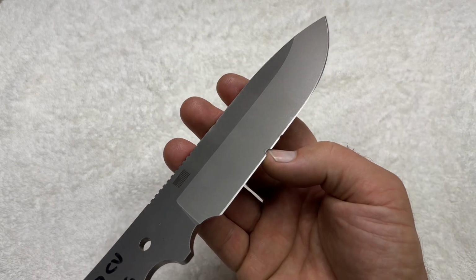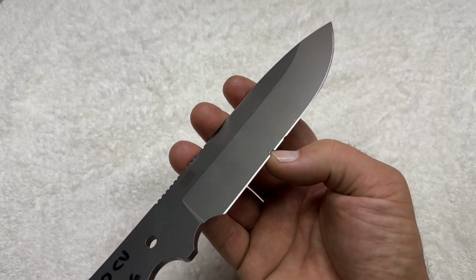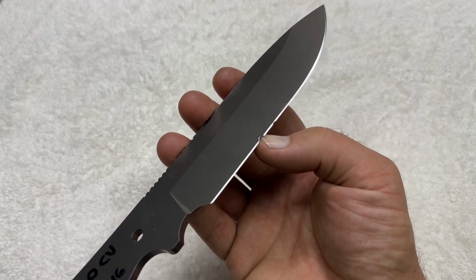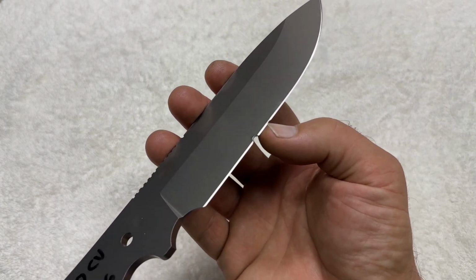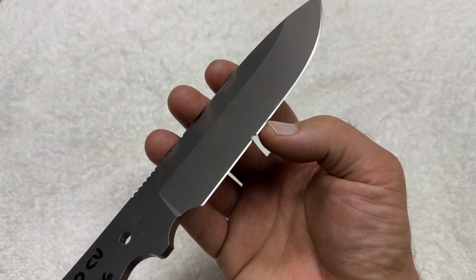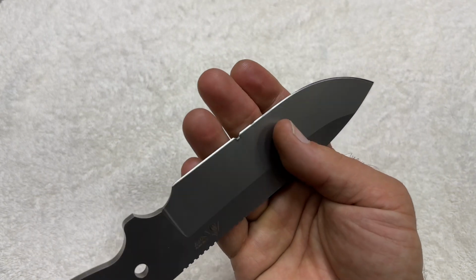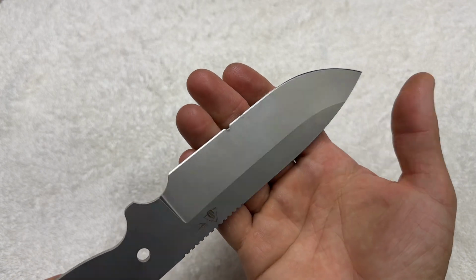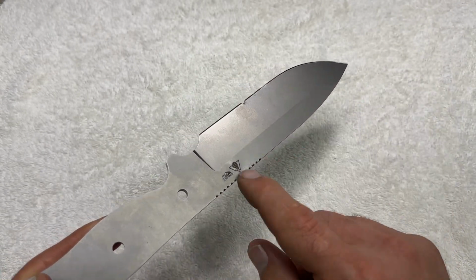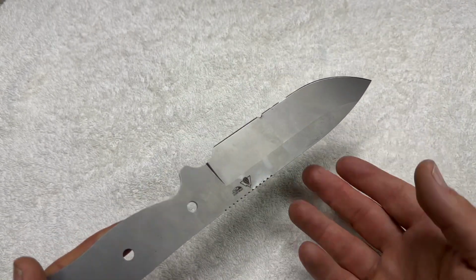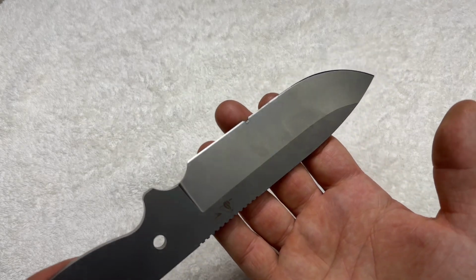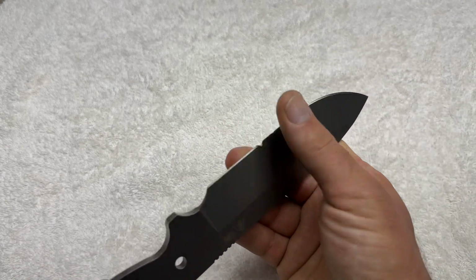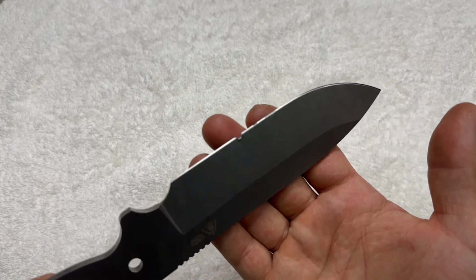So that failure was totally expected, and I just really took my edge out with a nail just to force a failure. But if you take your time and work through a nail, this is a really good steel. And on the M390 side of the same composition, just a third generation particle steel, really tightly controlled batches and a very homogeneous, fine grained material.